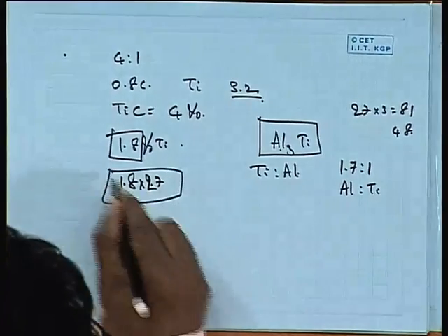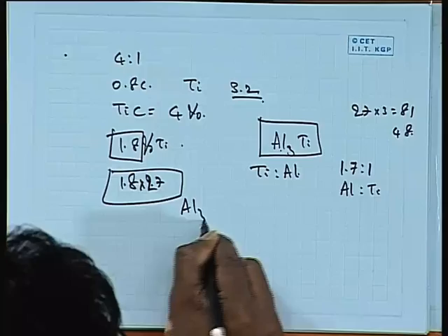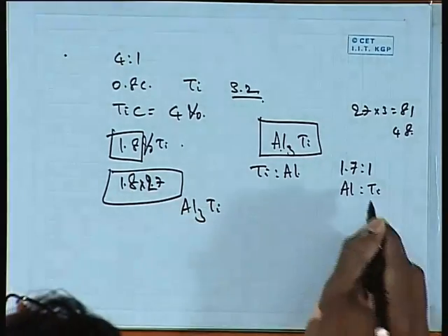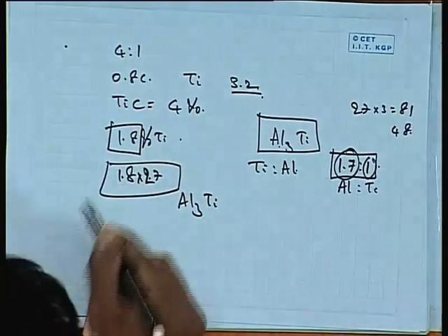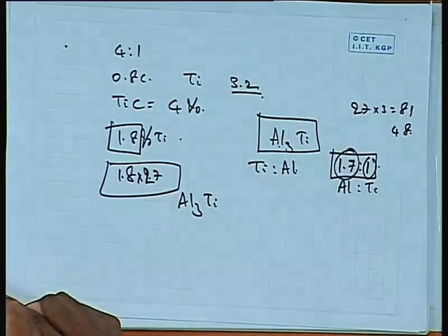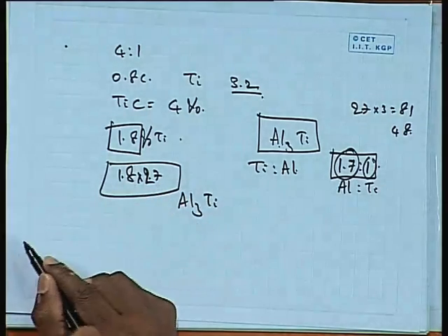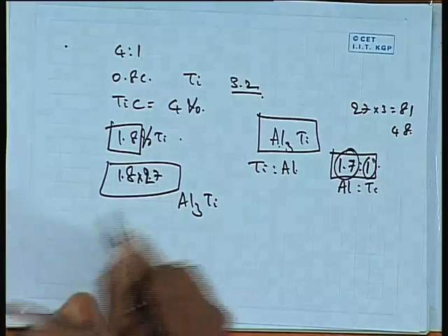So, this will give you the total volume weight fraction of Al3Ti that one can get, is it not, because 1 of titanium, 1.7 of aluminum. So, 2.7 is the total. So, if you take titanium as 1.8 multiplied by 2.7, you get something like about 4% or 5% or so, okay, double of this 5%. So, that 5% volume fraction is too small to see in an XRD if you take the composite, but once you have extracted the particles out of the composite, now aluminum has gone. So, whatever particles have been extracted, in those particles you can see easily whether there is TiAl3 or TiC.